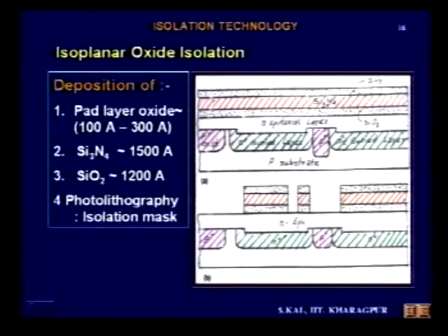Next, because this is basically the isoplanar bipolar transistor process, the buried layer is formed and the channel stopper is formed; those points I will discuss in the bipolar process. So on the epitaxial layer, the tri-layer structure is formed, then lithography. In the lithography, you see here, this region where you need the LOCOS isolation, the tri-layer oxide, nitride, oxide structure is removed in this portion and this portion. First you etch silicon dioxide, then when you are patterning, at the beginning there was a photoresist layer on top.